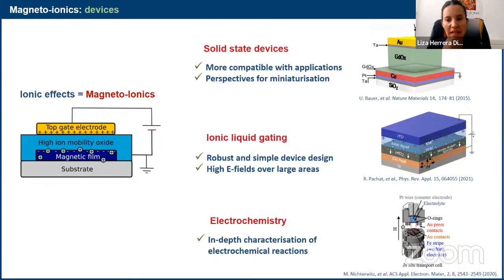This makes it particularly interesting to study magnetoionics with techniques like XPS, X-rays, BLS, techniques that need a relatively big chunk of material to get a good signal. So this is really what you want. Another important point is that the ionic liquid itself does not participate in the ionic process that modifies the magnetic properties. Here we have the hafnium oxide, which is the material that has mobile oxygen inside, and it's that oxygen that's going to move to the cobalt and boron. The ionic liquid itself would stop at the interface and will not diffuse into the stack.